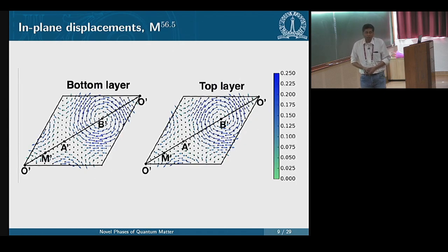Okay. So then what you can do is you're doing a DFT, you let the thing relax. This is maybe 1500 atoms, about the limit of what we can relax in DFT. And you ask, how did the atoms really move? I construct it by a rigid rotation, and then I let all the atoms move and see where they finally end up. What we thought initially was, okay, it'll move out of plane. After all, that should be fairly soft to move. But really, it should not move in plane, because that will cause strains within each layer. But turns out it actually does move in plane.